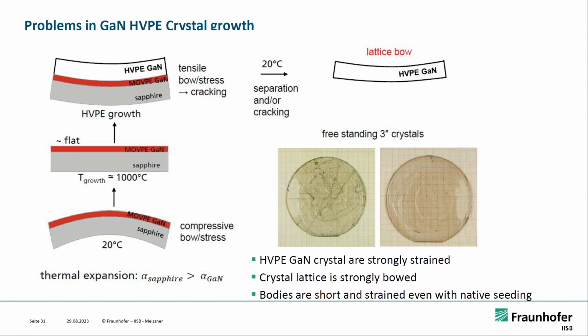So the issue is that for the HVPE material, you start on a 2-inch, for example, because you want to get a larger wafer and use 4-inch, and there's no native 4-inch gallium nitride existing. So you start on a sapphire, you seed it on a sapphire, and you have an HVPE gallium nitride thick crystal on top of it, up to 10 millimeters, and it makes the whole thing bow.